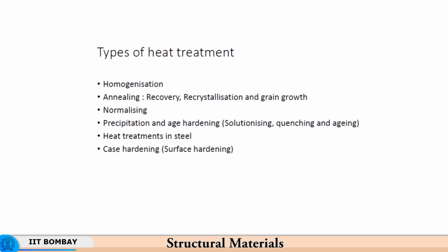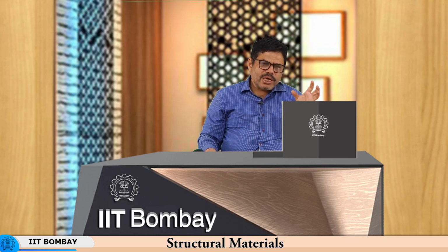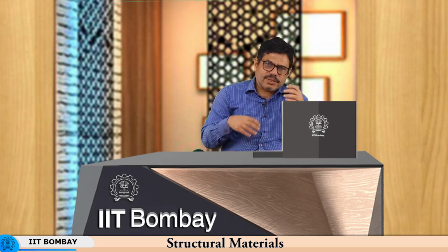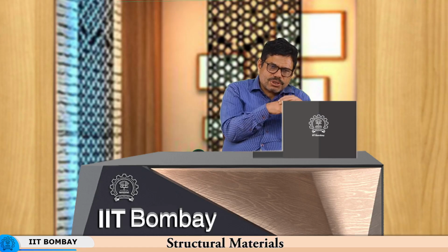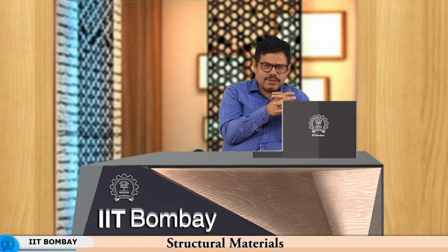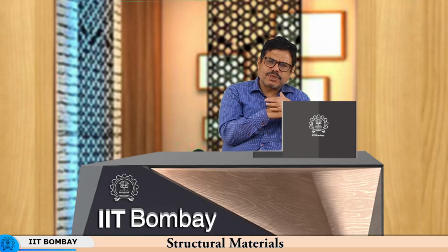So, now if you put all these alloying elements into a solution and then you quench it, when you do quenching, there is no time for diffusion of these elements, plus the temperature decreases very rapidly, and therefore, the driving force for diffusion is lost. So, the alloying elements which are sitting in the solution continue to remain in the solution. So, if the alloying elements have got dissolved in the single phase in the solid solution, they have no chance of forming any other phases. So, there is a single phase which has all the alloying elements residing in it. That is what happens when you quench the material, you do not let the diffusion take place.